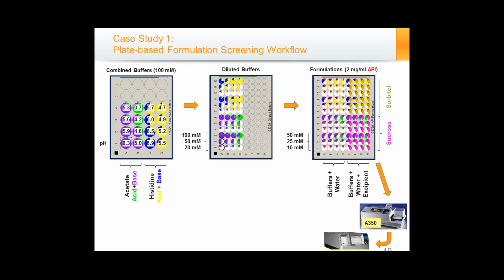And the DLS actually does two things. It will start by collecting dynamic light scattering information for every well, and then we go through a temperature ramp where we start at room temperature and step through until we get to 68 degrees Celsius, and we collect DLS data at each one of those time points. And in the end, we recollect the turbidity data to see if any of the formulations have become turbid as a function of heat stress.